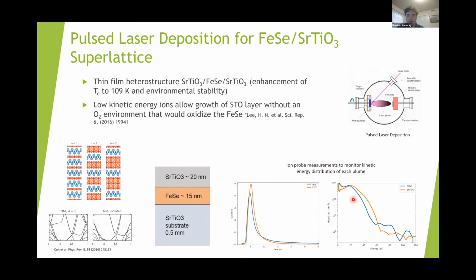And here I'll show ion probe measurements from the Langmuir probe, in which these are the normal current pulses we get from the ions hitting the probe. And this is the typical kinetic energy distributions for the iron selenide and strontium titanate species.